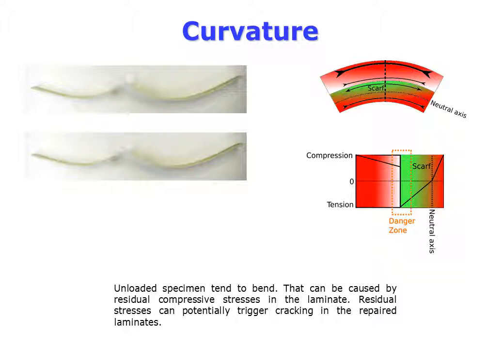It was observed that the samples tend to bend after testing. We assume that the bending of samples is a result of residual stresses caused by different heatings in scarf and parent laminate.